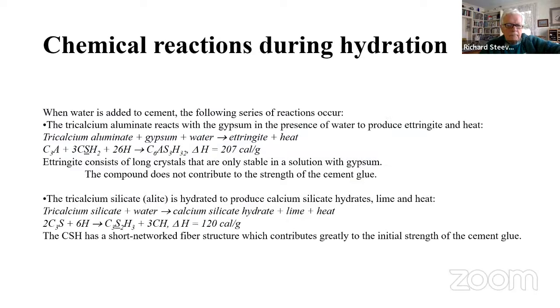And I'm gonna go through this in a little bit of detail because I personally found it interesting. This is the chemistry that occurs when you add water to cement. So this tricalcium aluminate first reacts with the gypsum. Remember, the gypsum has sulfate in it. I think everybody knows that gypsum is what you make wallboard out of, or sheetrock. It's in sheetrock. And with this water, it produces this compound that's called ettringite, and it actually also releases quite a bit of heat.